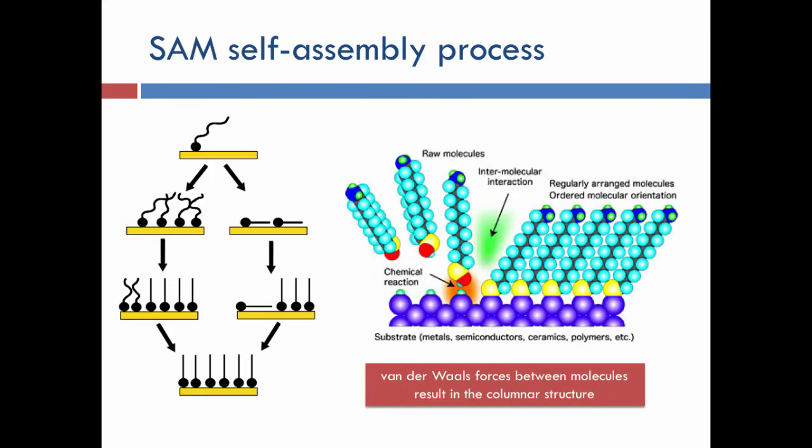Now, what does this look like when it's actually forming, right? So we talked about putting a substrate in a solution, which of course will have a random set of these molecules. Well, if you look at just one portion of the substrate and imagine the initial time right after the substrate's put in, well, there would be a very first molecule that would come, and the part of the molecule, most likely the polar part, would bond very strongly with the substrate.